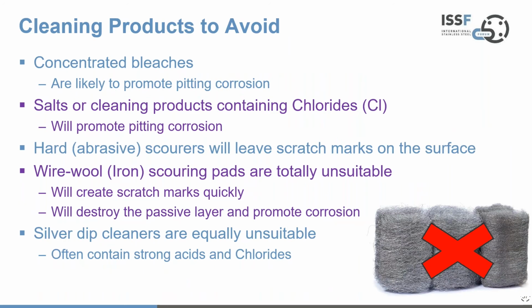But there are some things to avoid. So concentrated bleaches, worth avoiding because they're likely to promote pitting corrosion, which I talked about earlier in this webinar. Salt-based cleaning products known to contain chlorides will also promote pitting corrosion. Hard abrasive scourers will leave scratch marks on the surface, and that's unattractive, so not desired.